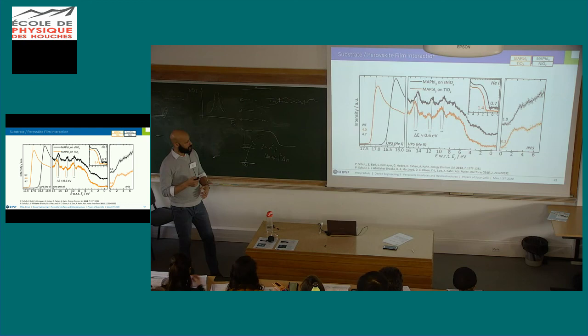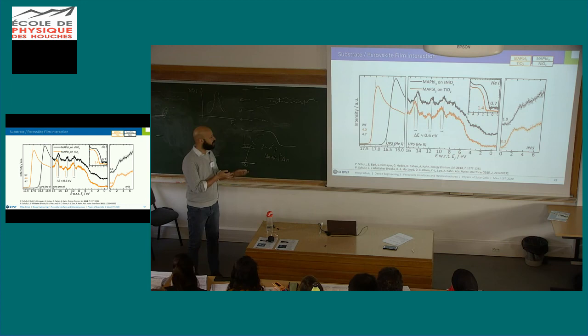In any case, also bear in mind the techniques are surface sensitive and the perovskite film is 400 nanometers thick. So we only get signal from the first 2 nanometers, the surface, but the electronic properties are determined by how you made your bottom substrate. And in the case of nickel oxide, you force it to be intrinsic or slightly P-type. And this is also why you could use nickel oxide easily in the tandem configuration and make a PIN junction for the perovskite on top of silicon that is terminated with an N contact.